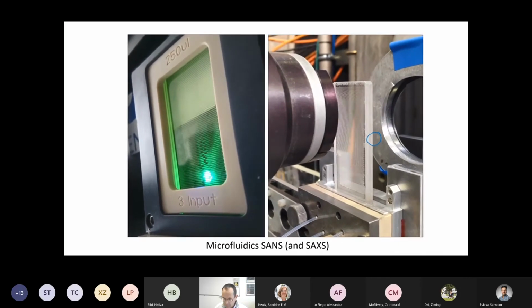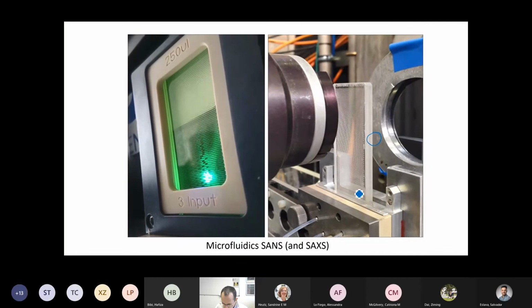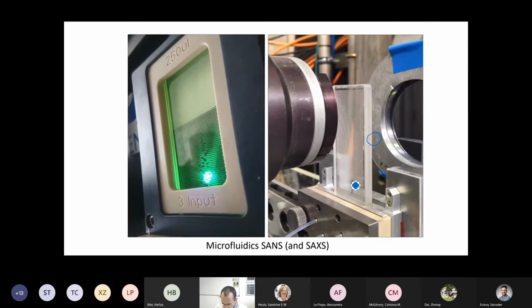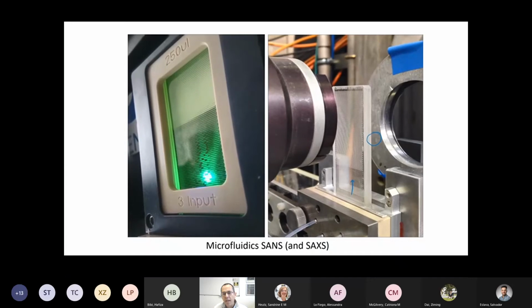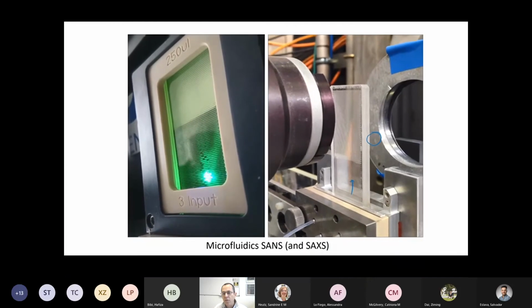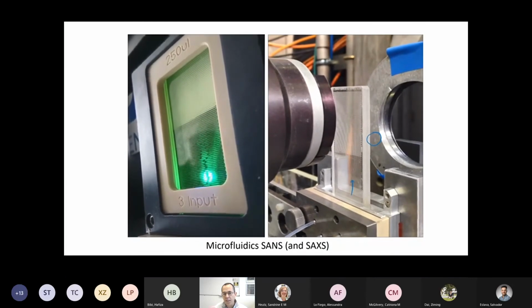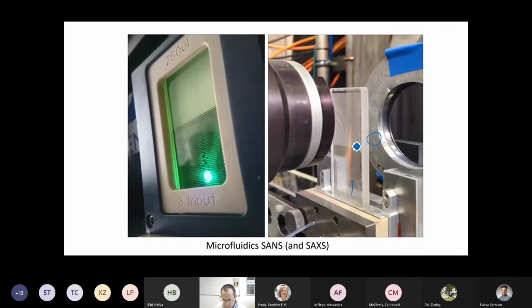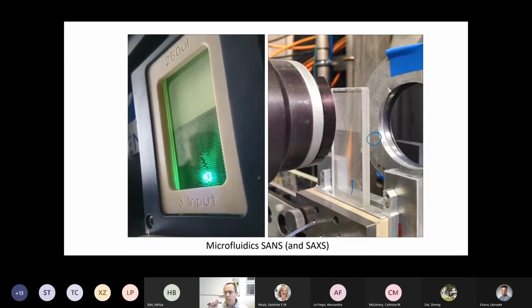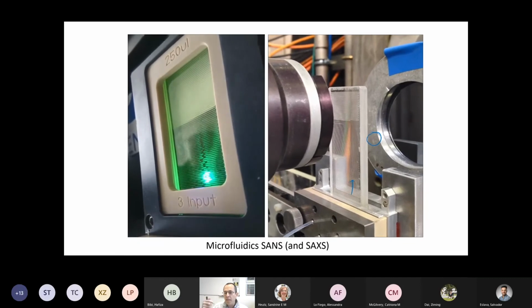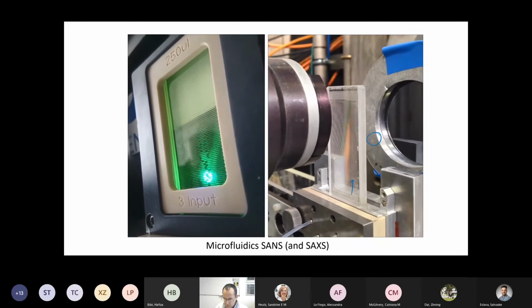We needed this to be transparent, but if you look at this sort of moving up, you can see these droplets are starting to fill up these. This is a special low boron type glass that doesn't really scatter neutrons significantly, so all the signal comes from the sample. And here you see a constellation of droplets moving across our field of view. And you can scan, therefore, spatiotemporally the evolution at the molecular level that these solutions undergo.